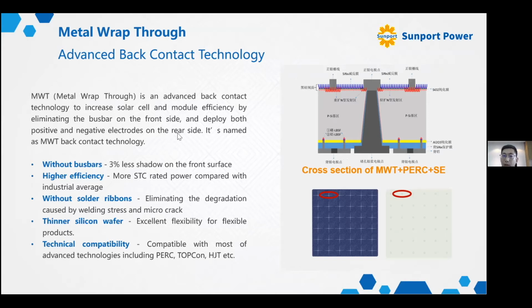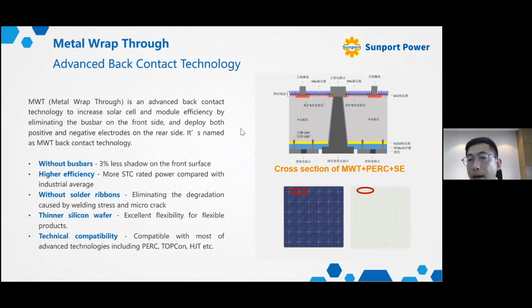We applied PERC and also selective emitter, which is so-called SE, on the MWT base. This ensures that our cells have at least absolute 0.3% more efficiency than those who don't apply back contact. The via array here and the paste within them direct the current from the front to the back. As a result, we have less shading area and higher solar cell module efficiency.